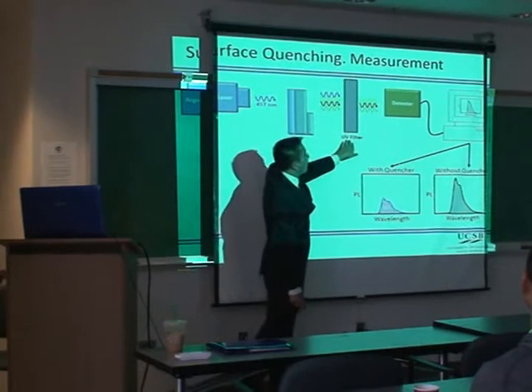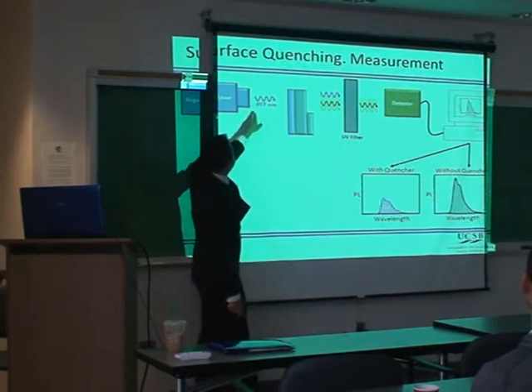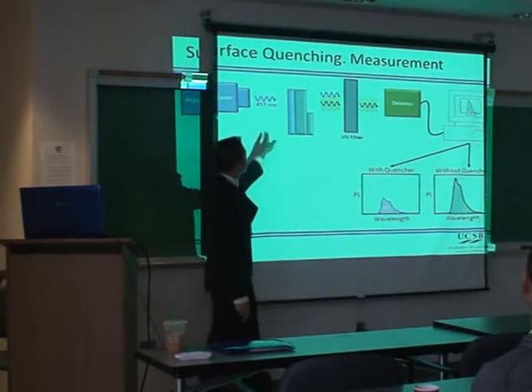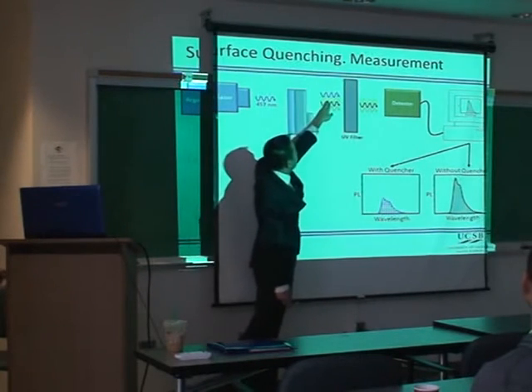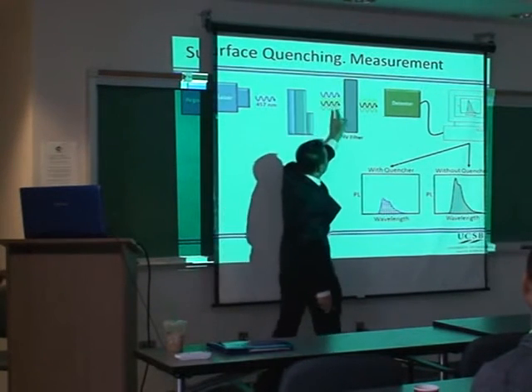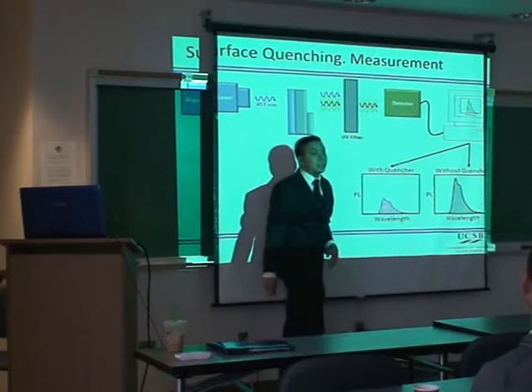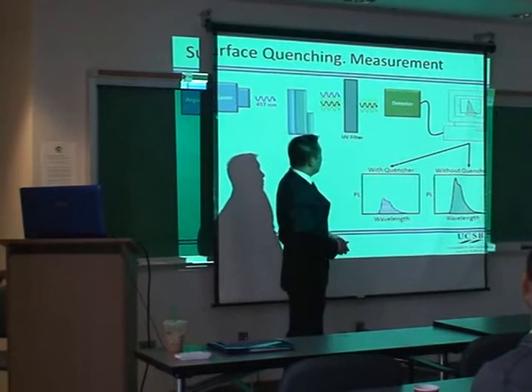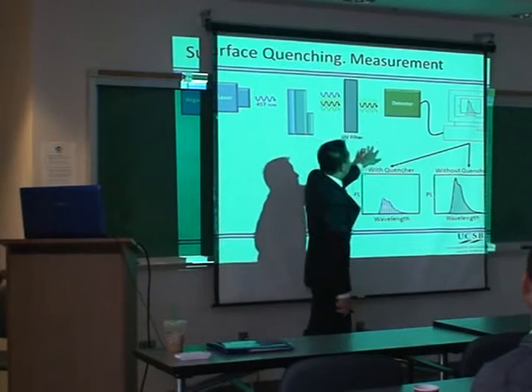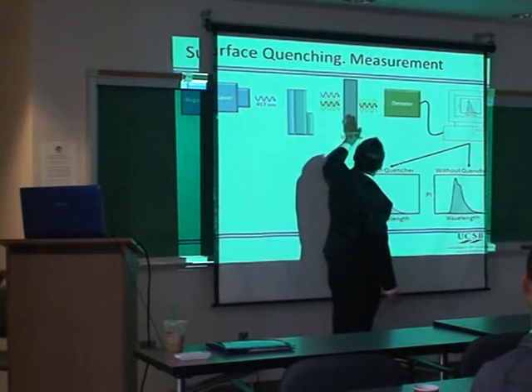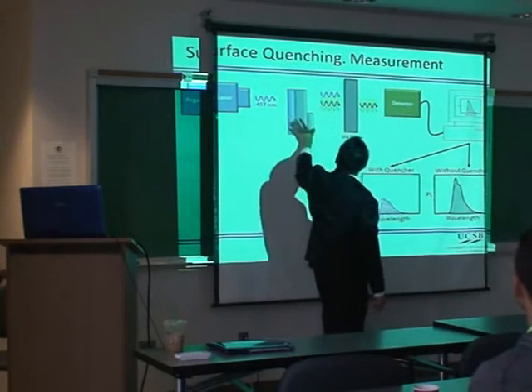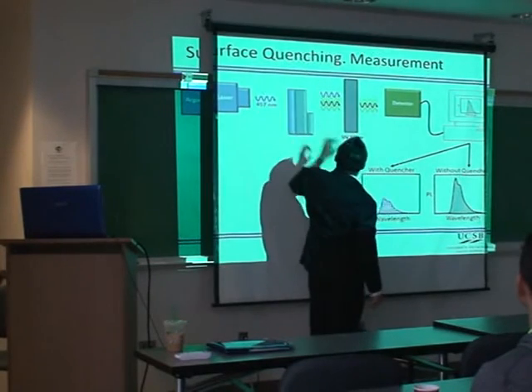What we then might do is also add a filter, because this UV light is actually quite strong. Some of it won't even be absorbed by this film and will just pass right through. And we don't want that to go all the way to the detector, because the detector is actually very expensive and very sensitive. So we don't want it to ruin our detector. So we filter out the UV, and we only record the fluorescence that comes from this film alone. We don't want any light from the laser.